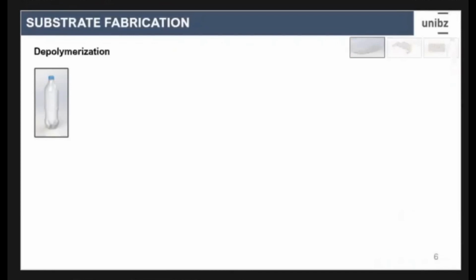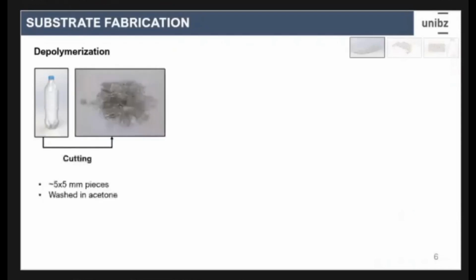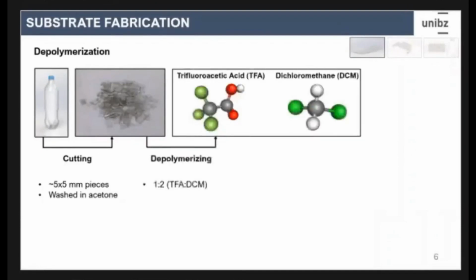So for this reason, we chose the chemical process where we took a bottle. Actually, the one you're going to see here, I drank a Coca-Cola in the morning, and that's the plastic I used to develop the substrate. After that, I chopped it into small pieces of approximately 5 by 5 millimeters square, and washed it with acetone to remove any impurities or glue from the labeling of the package to have as pure a plastic as possible. After that, you mix it with trifluoroacetic acid (TFA) and dichloromethane in a 1:2 ratio to depolymerize the PET.